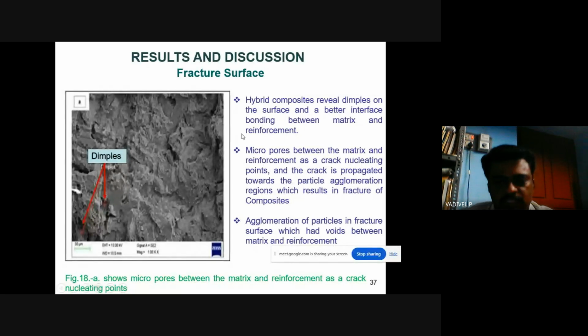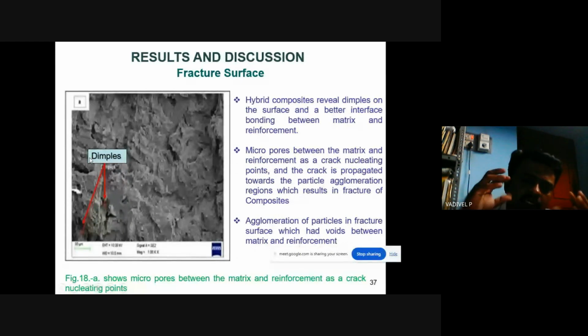The hybrid composites had dimples on the surfaces. This indicates better interface bonding between the matrix and the reinforcements. Because of these dimples, it is confirmed that there is better bonding between the matrix and the reinforcement. The micro pores between the matrix and the reinforcement act as crack nucleating points, and the crack propagates towards the particle agglomeration regions, which results in the fracture of the composites.